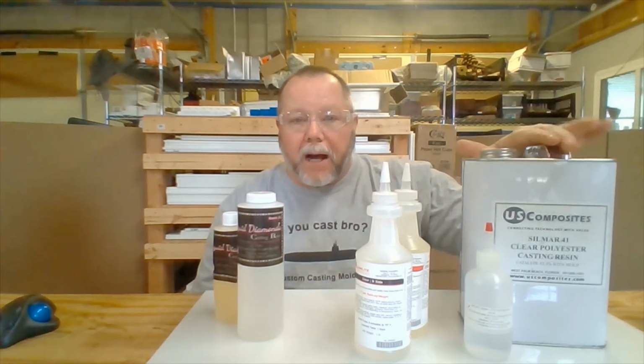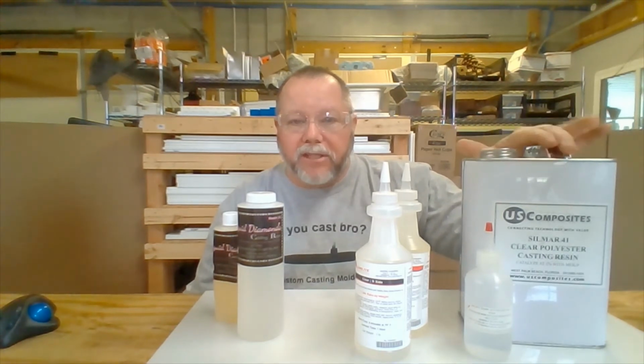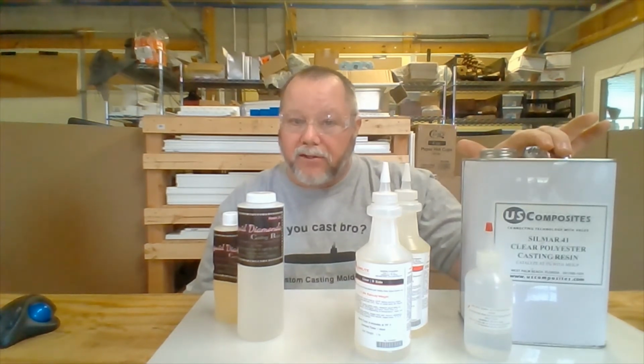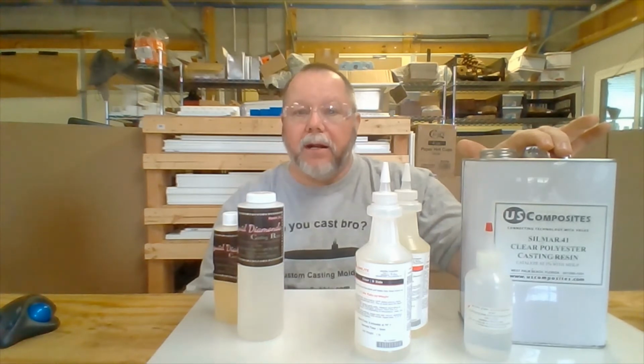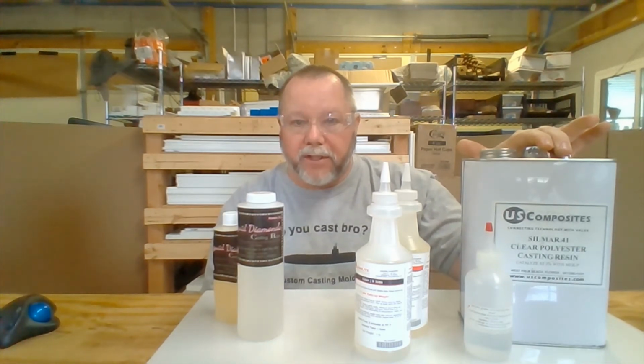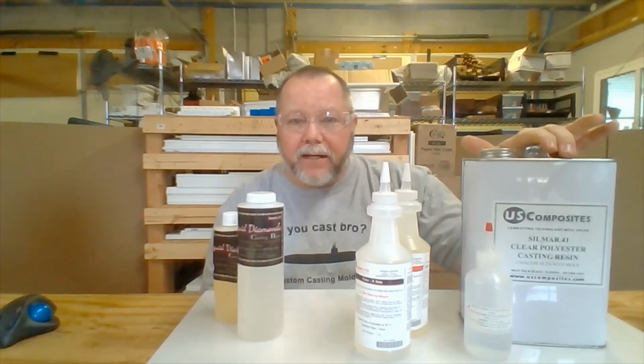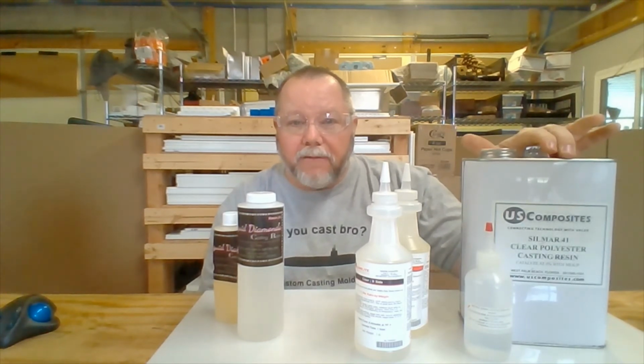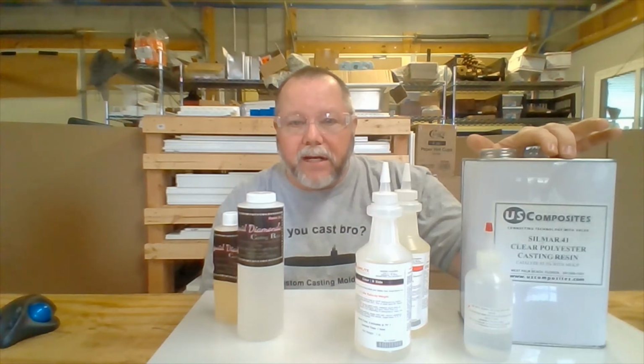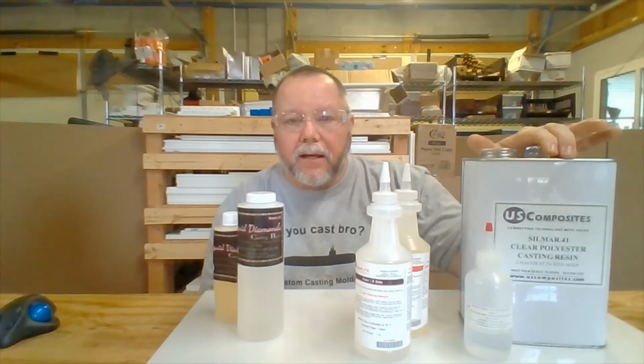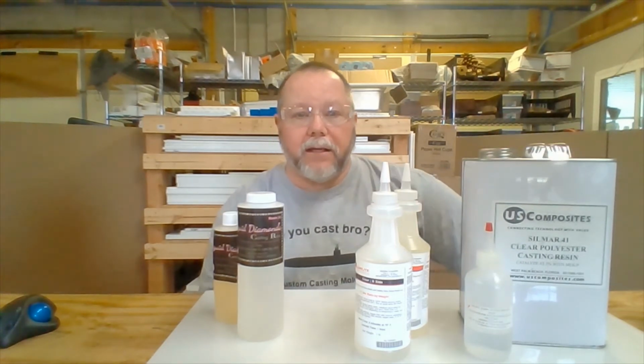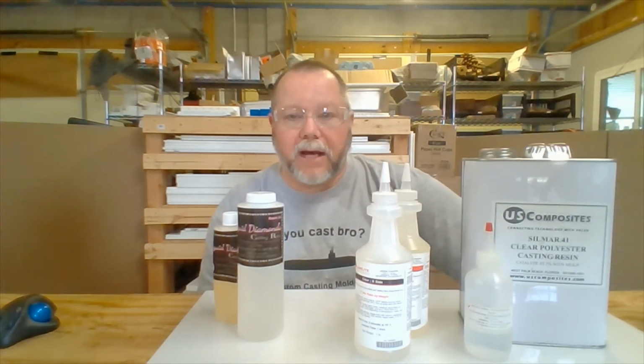So polyester resin will also cure tacky on the top. That's so that you can cast, again, another layer on top of it, and it will cure to itself. If that tackiness is there, set it outside in the sun for 10-15 minutes if you're in a very sunny area, or put it in a toaster oven at 150 degrees for 15-20 minutes, and that gets rid of the tackiness on the top.